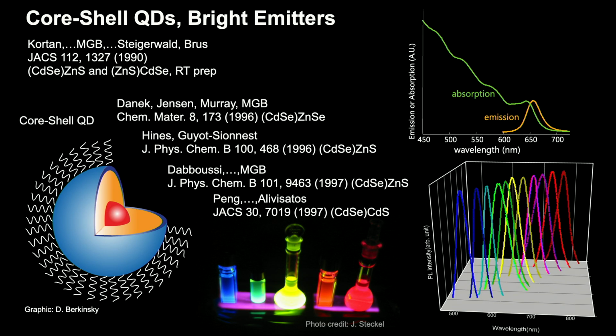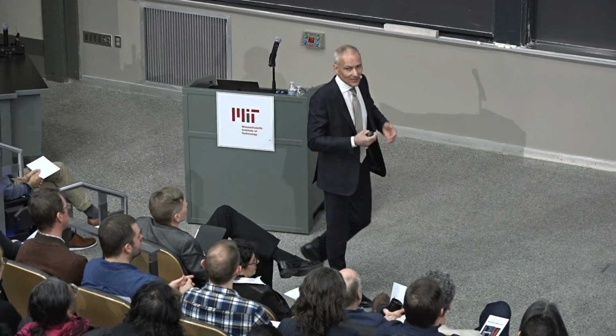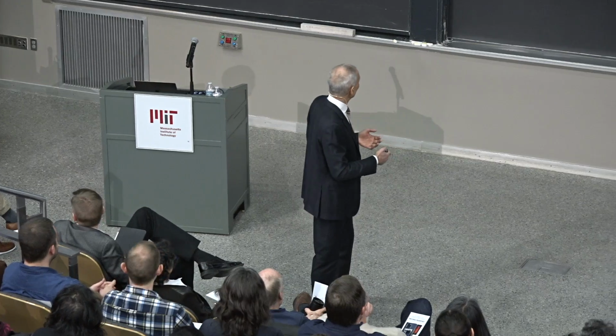So there were a number of groups, including myself. Philippe Guyot-Sionnest at Chicago was the first to break the 50% quantum yield here. Today, the same scheme of a core shell allows us to make particles that have 100% quantum yield. So they're no longer trash, right? Right, and that's what's in the TVs. The Samsung TVs have particles that have 100% quantum yield that gives them their green and red color. And so now you can have a size series, or change the material, because cadmium selenide isn't the only material. The TVs have indium phosphide in them, for instance. By changing the material and the size.